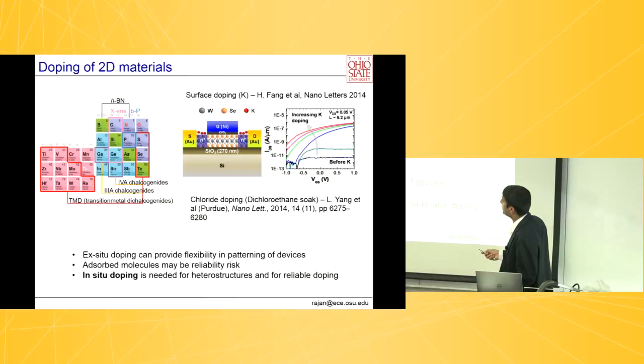With molybdenum, rhenium is going to be hard because of the size difference, but that could be another thing to try. I think we did get a sputter source, but for tungsten it'll be much easier to put rhenium in to dope it. Right now, the only thing confirmed by several groups is niobium on molybdenum, which works as expected. But chlorine on sulfur works too, so you can go there also.